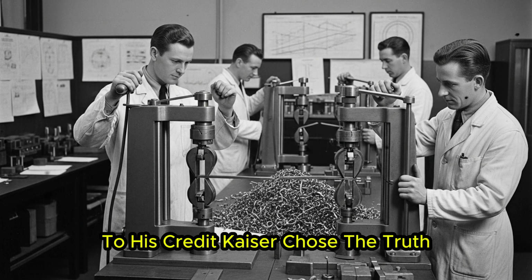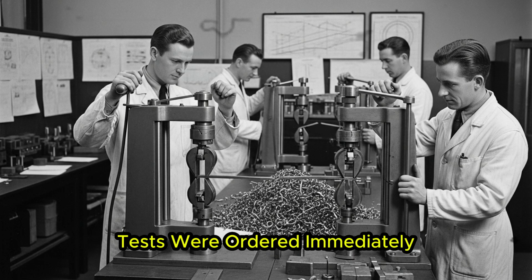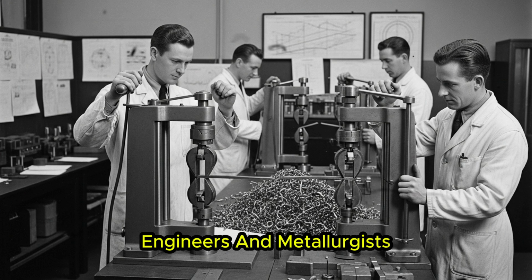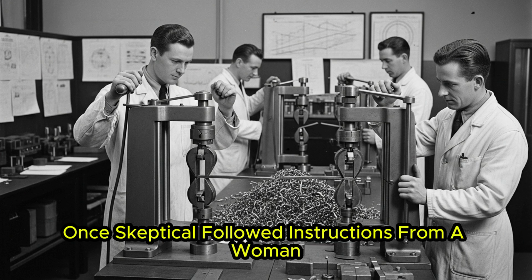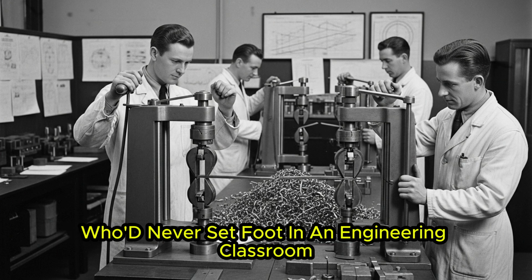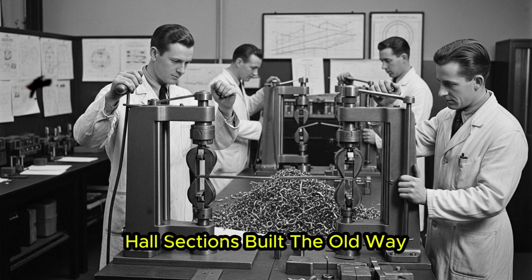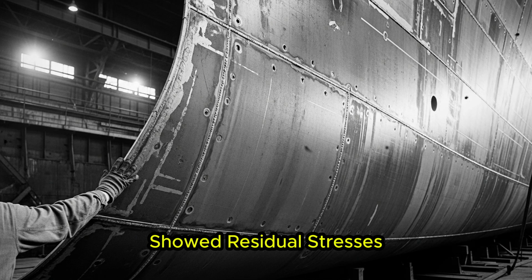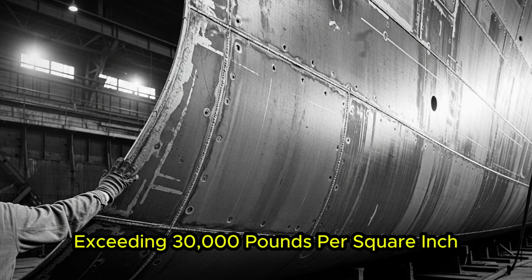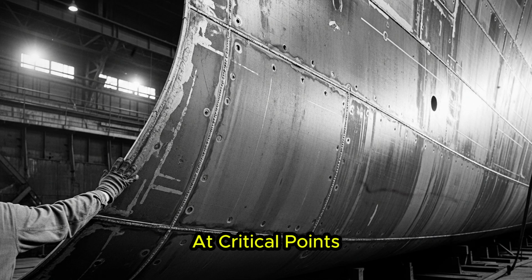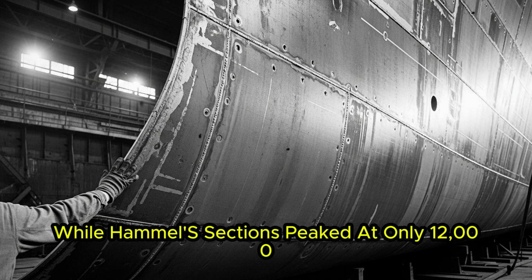To his credit, Kaiser chose the truth. Tests were ordered immediately. Engineers and metallurgists, once skeptical, followed instructions from a woman who'd never set foot in an engineering classroom. The results were startling. Hull sections built the old way showed residual stresses exceeding 30,000 pounds per square inch at critical points, while Hamill's sections peaked at only 12,000.